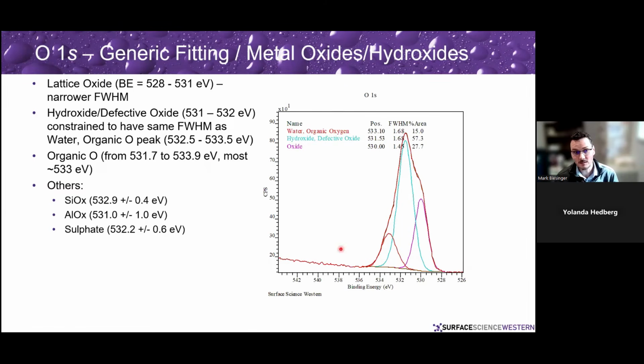I've got organic oxygen that could be in this area here. If there's silicon or silicone present, that's going to be at a certain binding energy, and you may want to factor that in. If you've got the survey spectrum and you know what it is, you can actually do some calculations. Say I have 5% silicon in my survey spectrum, and I know it's silicon dioxide. So therefore, 10 atomic percent of the oxygen in the survey scan should be silicon dioxide. I have a 60% oxygen peak in the survey spectrum, and 10 out of 60 is silicon dioxide. So I can fit that in, constrain it, and say I know so much percent of this peak is silicon dioxide.